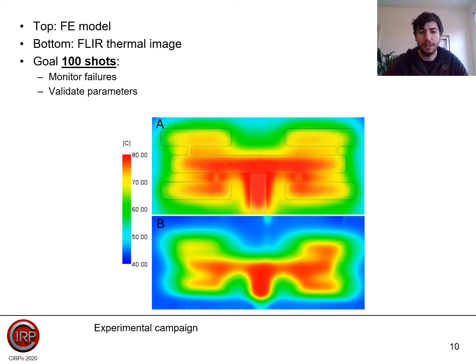The hypothesis that shear stresses and thermal loads are responsible for premature mold failure is validated according to a well-monitored experimental campaign, based on the optimized design. Specifically, it is expected that in case first failure of the molds occurs in the 1 mm gate, shear rates are the predominant factor, since the highest shear rates occur at that place during the injection molding.